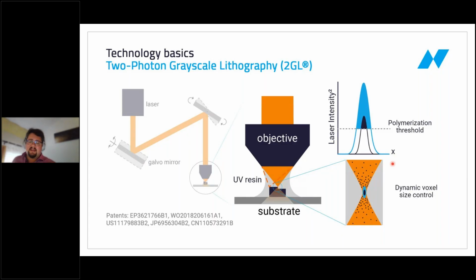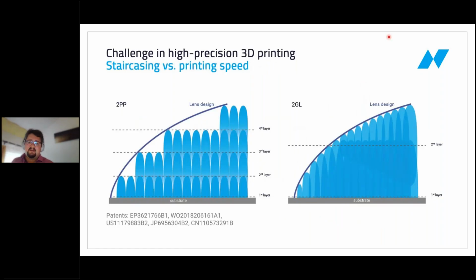If we now change the laser power, you can easily imagine that the line becomes smaller in all three directions. So by changing the laser power, we can change the total size of the voxel. This is also possible on Photonic Professional GT2. However, if you want to use this dynamically, you have to make sure, and this is something that we just learned afterwards, so this is now implemented in Quantum X, it is unfortunately not possible to retrofit. So now if you synchronize the galvo movement and make sure that you have real-time control of your voxel on the megahertz scale, you can actually get around this fundamental trade-off that I mentioned earlier.